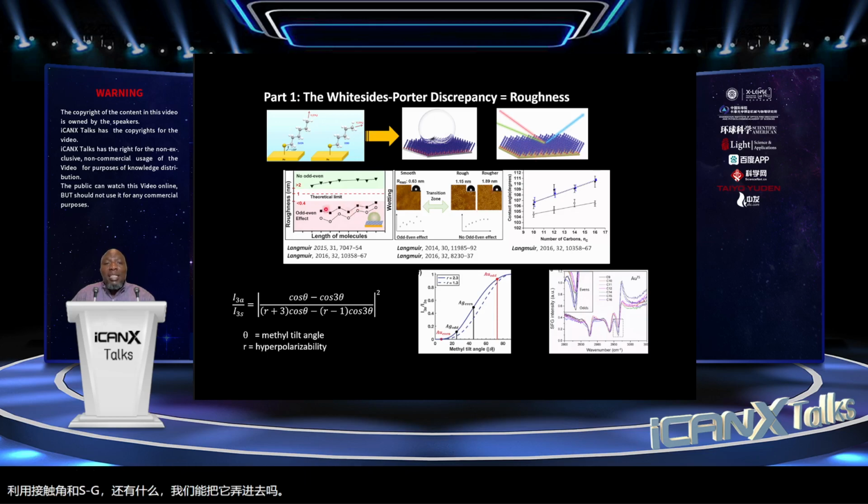We observe that the roughness of the surface plays such a critical role that as you get to a gold surface that has a roughness of 1 nanometer, this ability to distinguish these odd and even orientations in the CH3 group disappears. And we call that the theoretical limit to the odd-even observation.